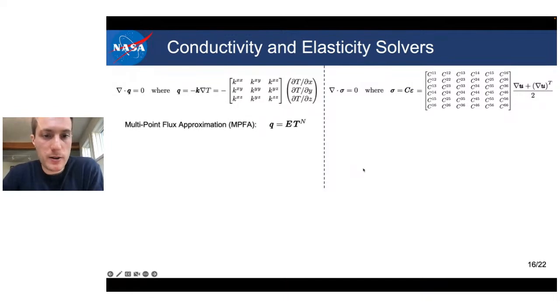Next, what we are using for the conductivity, for the local discretization of our finite volume scheme, is called the multi-point flux approximation, or MPFA, which is a pretty commonly used numerical method. This linearly approximates the fluxes to the local nodal temperatures through a transmissibility matrix. On the right-hand side, instead, is a multi-point stress approximation, which does the same between the stresses and the nodal displacements through a transmissibility matrix again.